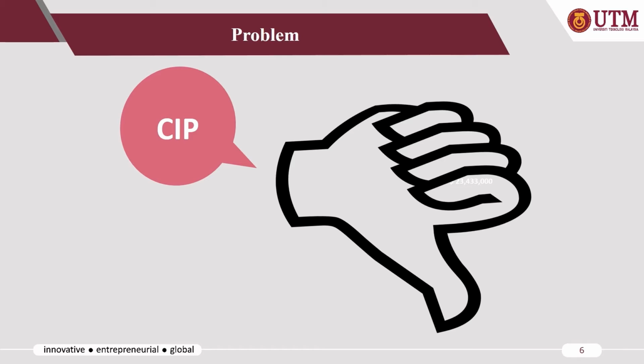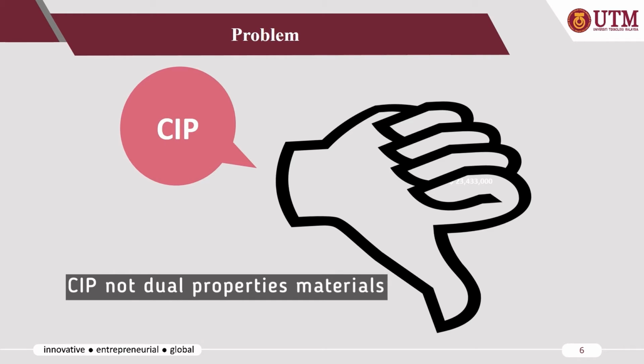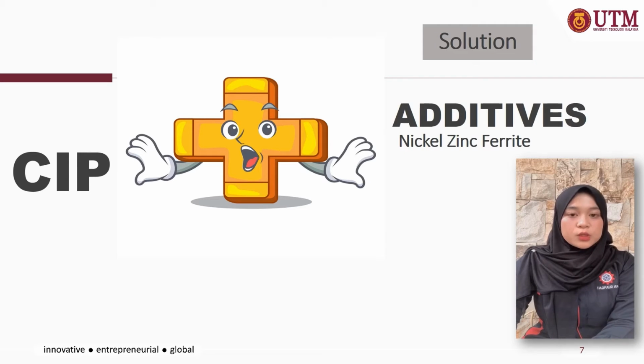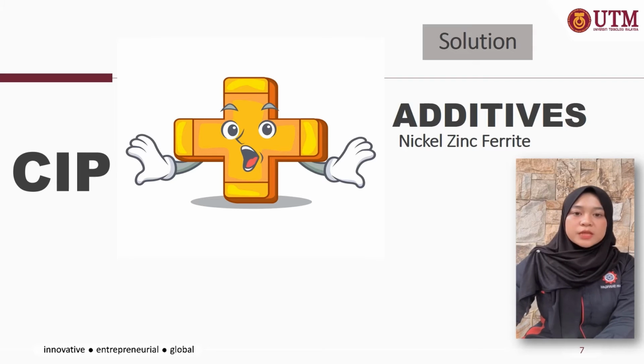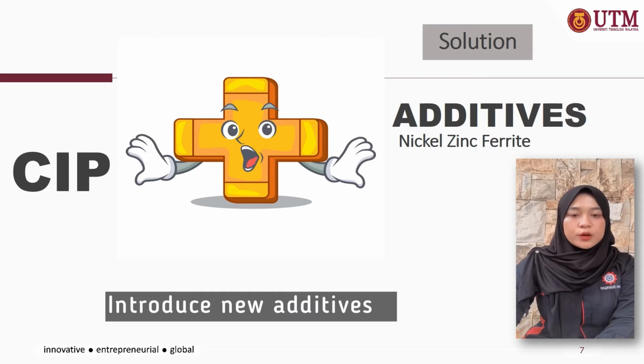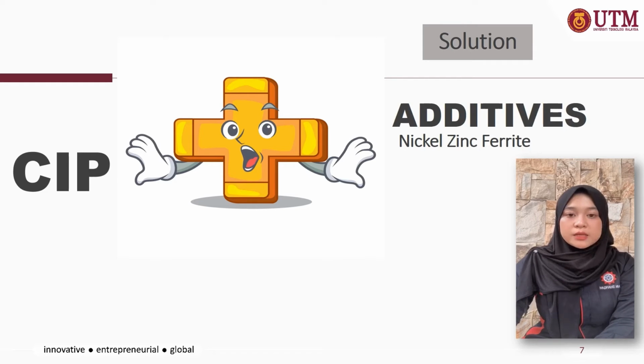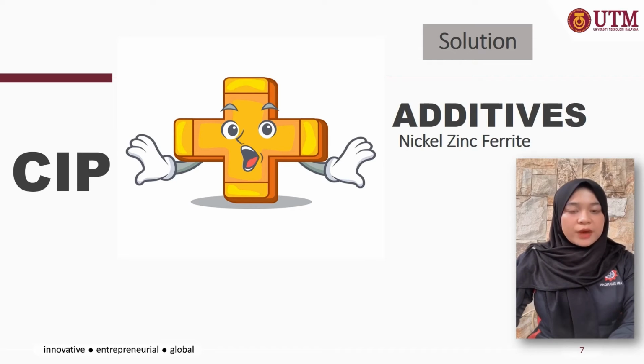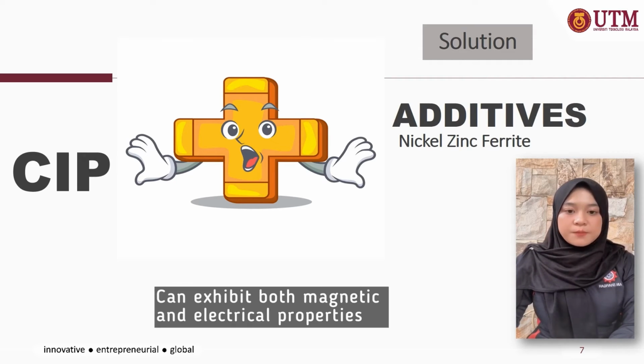I found out that there is a study about an MR prosthetic knee joint where previously the system applied MR fluid. Modification of the device, however, changed the material into MR elastomer due to a leakage issue. It was found that the magnetic performance towards the sensor is brilliant, but electrical performance is passive because CIP is not a dual properties material. Therefore, to overcome the limitation of CIP that does not actively respond towards the electrical field, this project introduces the synthesizing of a new additive, Nickel-Zinc-Ferrite nanoparticle. The combination of the additive and CIP particle is believed to exhibit dual properties of magnetic and electrical conductivity.